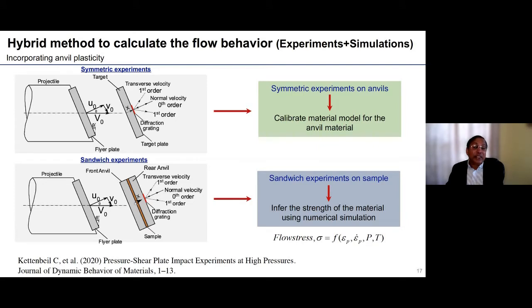Now we can conduct the experiments and again obtain the free surface velocity. Our normal response is dominated by the anvils, because the pressure is still being transmitted across the sample and the same pressure wave is propagating, only slightly altered by the presence of the sample. But the shearing response is now quite different from the symmetric experiments where we calibrate the anvils, because the shearing response is now dominated by the sample. This way we get the shearing response of the sample, and we get both the normal and the transverse velocities. This is how we infer the strength of the material, again using numerical simulations.